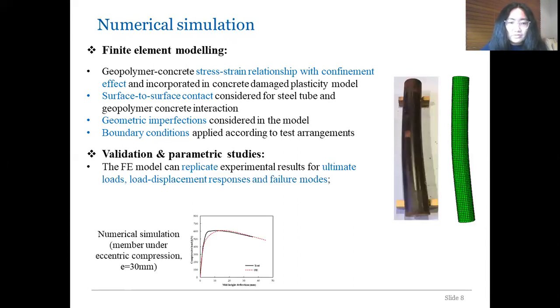The FE model was first validated using the experimental results I obtained through the research. And just to show a typical example of the FE model validation for a member tested on the eccentric compression with the eccentricity of 30 mm. As can be seen in this figure, the FE model can replicate the experimental results. And on the right-hand side, you can see that the global buckling failure was accurately traced by the FE model.